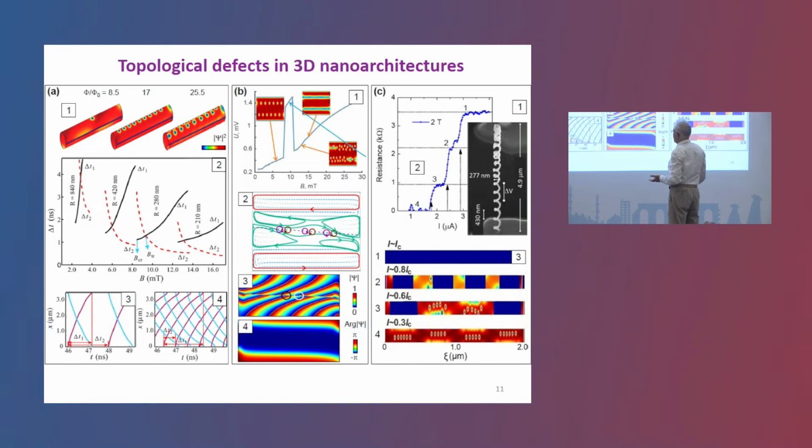So the difference between typical magnetic fields of transition between two regimes, or simply the starting of the motion of vortices, can be changed in the range of a numerical factor of 7 or even better. So it's not a small effect, it's a very pronounced effect.